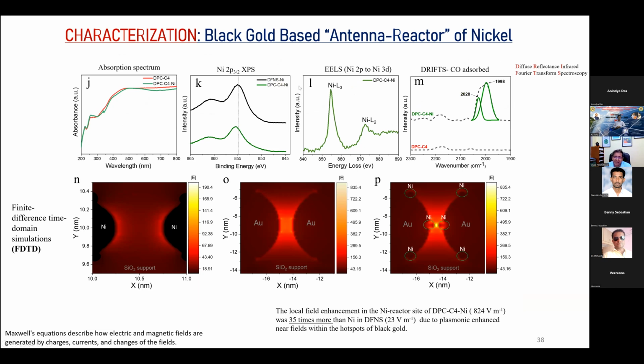XPS and EELS say that the nickel is in the 2+ state, which is ideally not possible because we have reduced it. So there was this confusing result. But then we realized that XPS and EELS are done in an open environment.